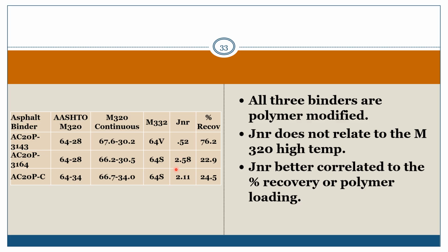These 2 particular ones are S grades. They're less than 4.5, but above the 2. This one particular 6428, though, now we see the Jnr is 0.52. It's significantly less. It's almost an E grade. So that's why you have 64V. But now we take a look at the percent recovery, and it sort of gives you an explanation of why